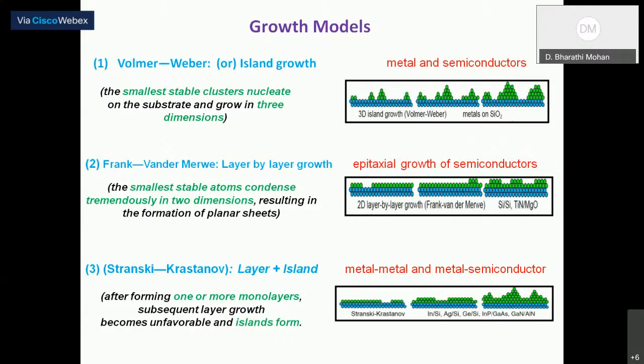When you form a film using any deposition technique, there are 3 models involved. The first one is the Volmer-Weber growth, or one can call it the island growth model. In this model, the smallest stable clusters nucleate on the substrate and grow in 3 dimensions. Suppose you want to deposit metal on SiO2, you form an island type of growth. The second model is the Frank-van der Merwe model. It is also called layer by layer growth.